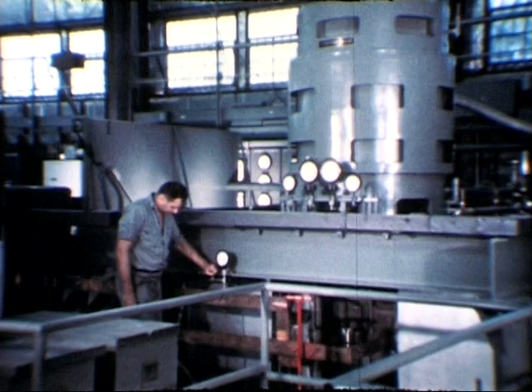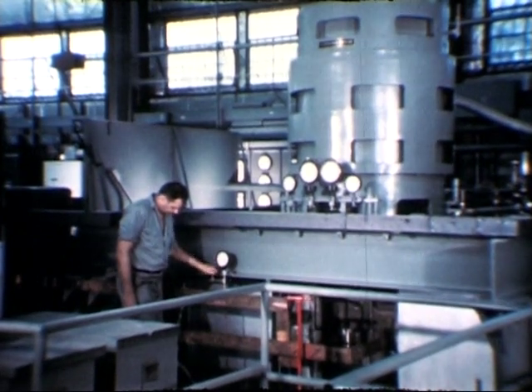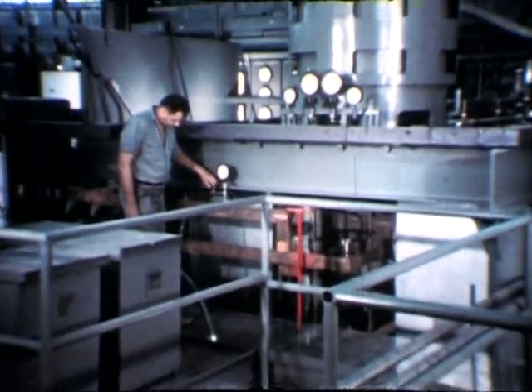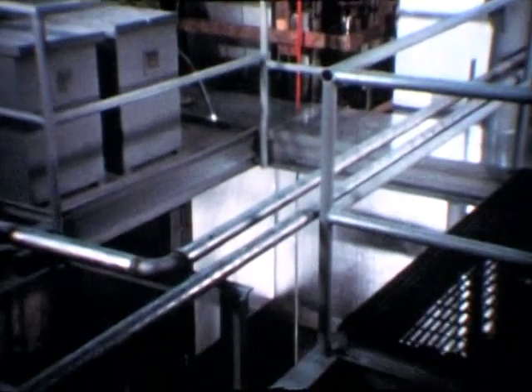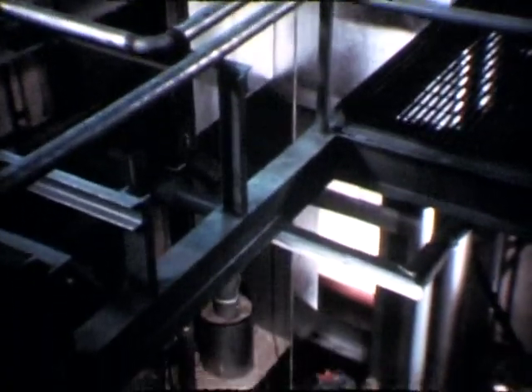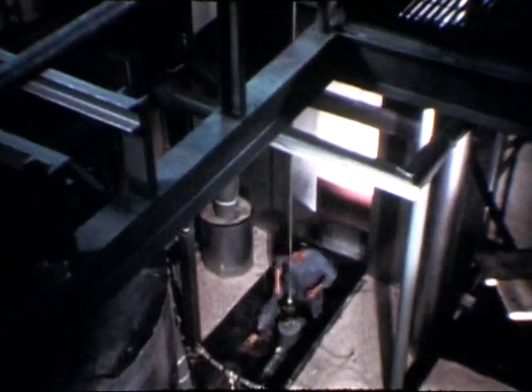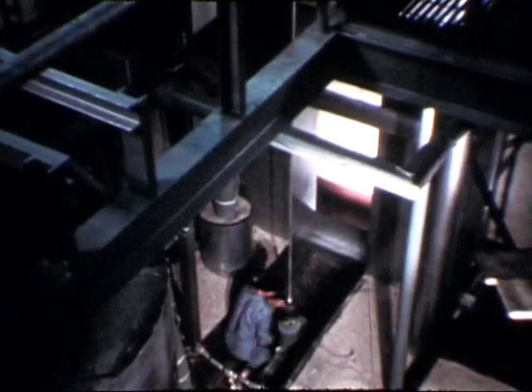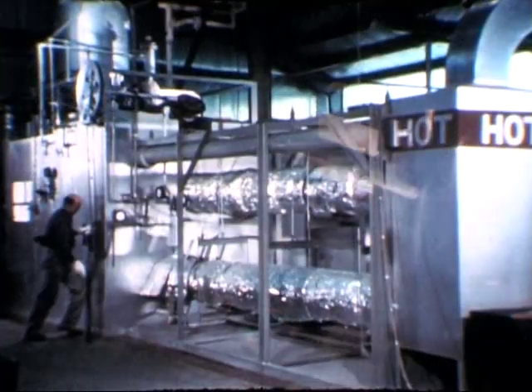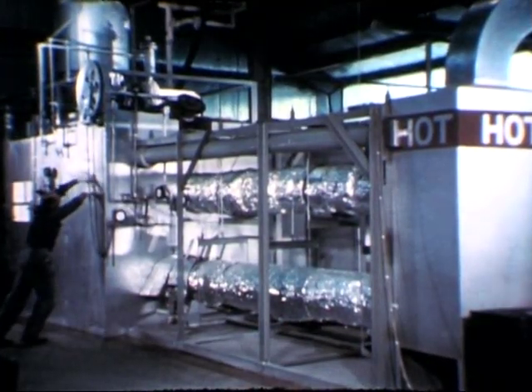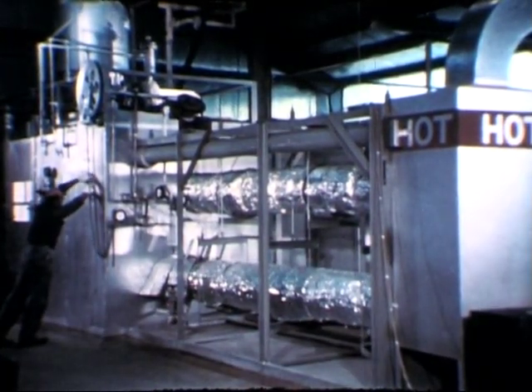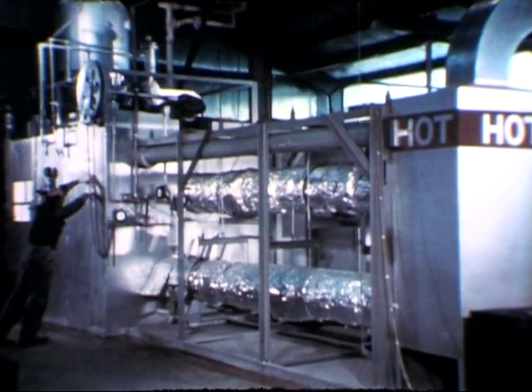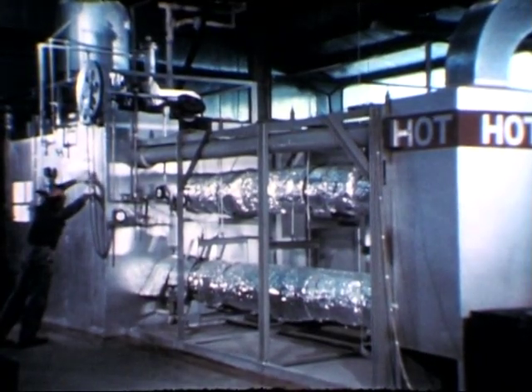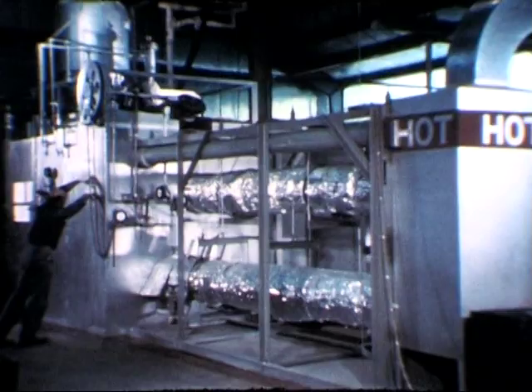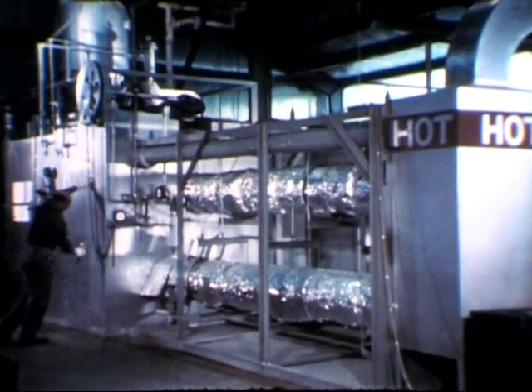A 250,000 ampere direct current homopolar generator and a 10,000 gallon per minute DC electromagnetic pump have been developed by the laboratory. Preliminary operation of this pump has shown overall pumping efficiencies of 20%. A 5,000 gallon per minute vertically mounted single stage centrifugal pump has had more than 6,000 hours of successful operation at 700 degrees Fahrenheit and a 40 psi head.